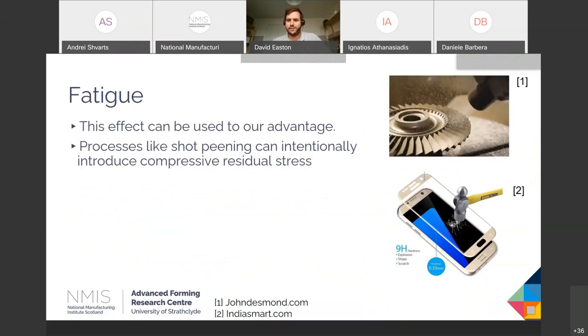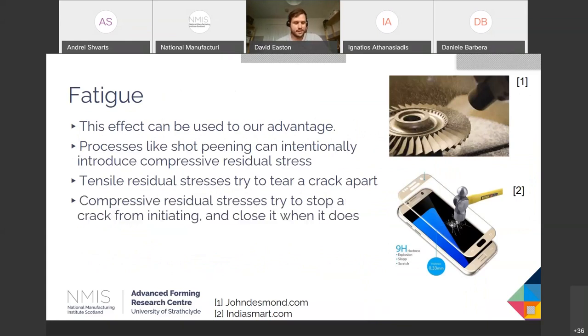Of course, this can be a benefit as well. We can use the compressive residual stresses on things like the shot peened gears or shot peened blades, things like this. It's also the reason why we can have glass screens that are as large and perform as well as they do today. Glass screens on phones would typically fracture at a much higher rate if it wasn't for the fact that they're treated in a way to give compressive residual stress on the surface of the glass. So they might still crack, but that crack isn't going to propagate through the entire screen like it would if it was otherwise untreated.